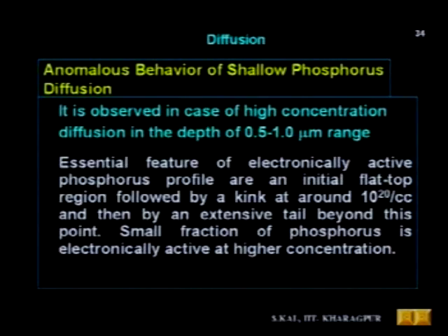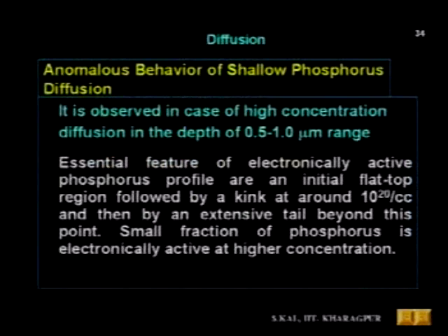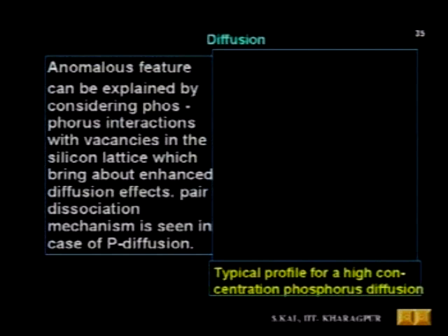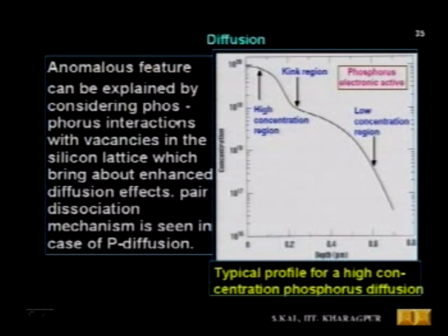Actually, electronically active phosphorus atoms diffuse into the silicon. So if we plot the electronically active phosphorus atoms versus depth, then we will see this anomalous behavior, and it is something like this. Here you can see the curve. This is the depth in micron, and this is the concentration, and electronically active phosphorus atoms are plotted here. This is the high concentration region near the surface, as I mentioned, near the 0.5 micron region. There you can see a flat region. After that flat region, you can find a kink region, and then a low concentration region. This is known as the tail region.